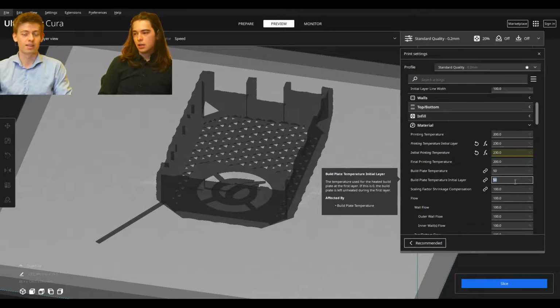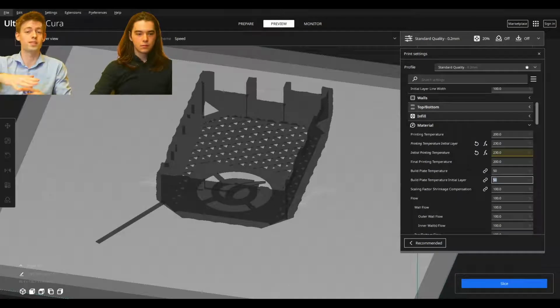Yeah. And also, sometimes people use a magnetic bed surface where, on an Ender 3, for example, you have your aluminum plate, and then a layer of glue or some sort of heat adhesive, and then you have your magnetic plate on there, and then your steel sheet that connects to the magnetic plate, maybe another layer of adhesive, and then your actual printing surface. And then there are all these different layers between the surface of your print bed and your heater, and that's going to cause a decent temperature offset. Maybe you even need to go to 70 degrees on your first layer. So you have to consider the thermal conditions of your bed.